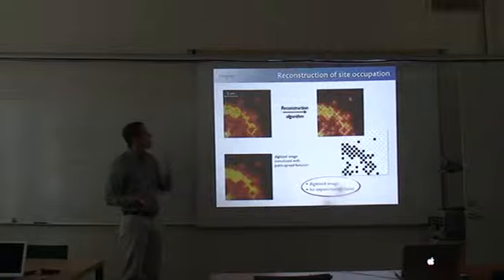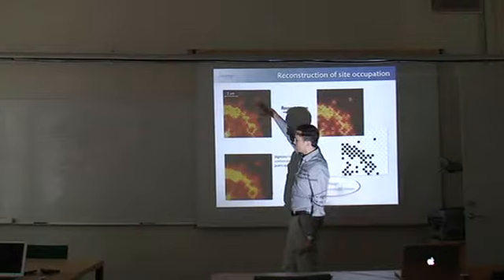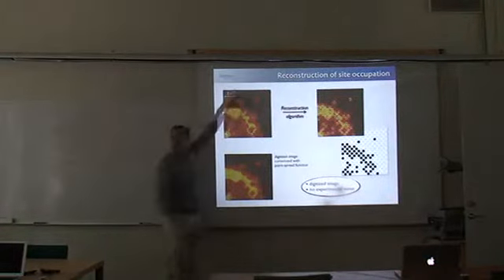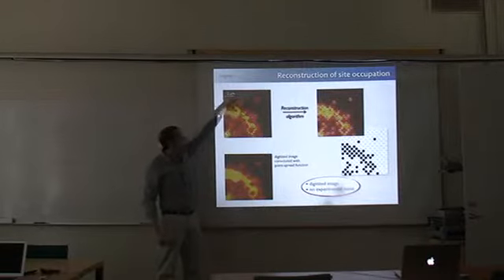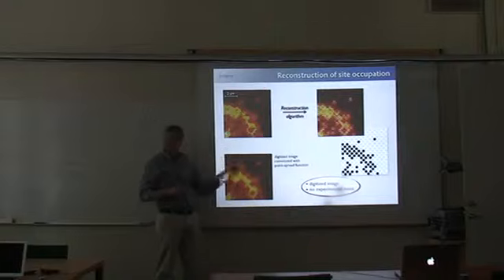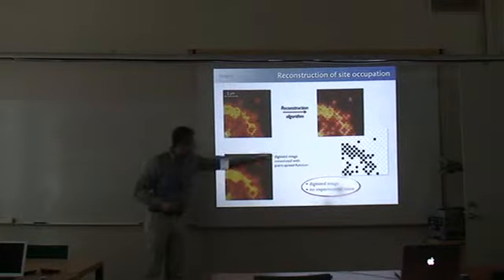No, I'm asking differently. So you say, okay, black is black. Then red is singly occupied. So you erase red and their contribution to yellow. Okay, so actually the protocol, how this reconstruction algorithm works, does the following. It goes blockwise through the system and tries out different atom number distributions. It knows what fluorescence image they will generate, because we know the point spread function. We know what a single atom is going to do. So for a given atom number distribution, we can create an artificial reconstruction of the image, and then I can just take the chi-square, the difference to my original image, and find the one which has the lowest chi-square.